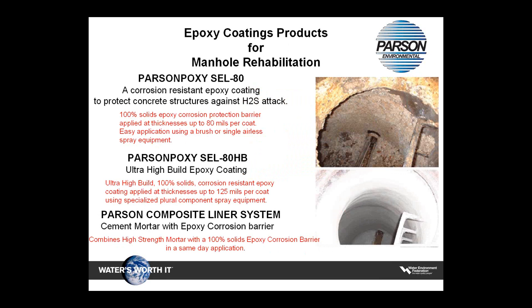Parson Epoxy SEL-80 is a high-build, 100% solids epoxy coating used for corrosion protection. The product can be brush or spray applied up to 80 mils thick in a single coat. Parson Epoxy SEL-80 HB is an ultra-high build, 100% solids epoxy coating with application thicknesses that can reach 125 mils per coat. Our composite liner system provides both structural integrity and corrosion protection with unique same-day application.